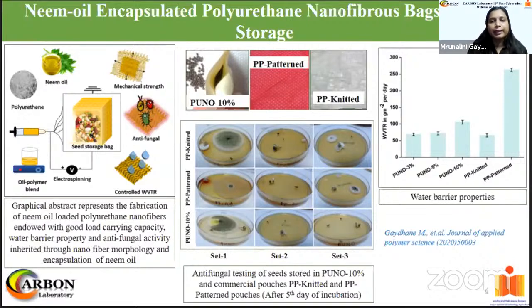When the real-time applicability of these bags was investigated, we found that after 75 days of seed storage, nearly 70% of seeds in commercial bags were infected with black mold or storage-borne fungi, whereas only 10% of seeds in nanofibrous bags were infected. The reason was found to be the controlled moisture transmission rate achieved through nanofibrous morphology and pesticidal property imparted by neem oil. This nanofabric bag shows great potential towards reducing the seed storage losses and may be a game changer for achieving food security as one of the goals for sustainable development.